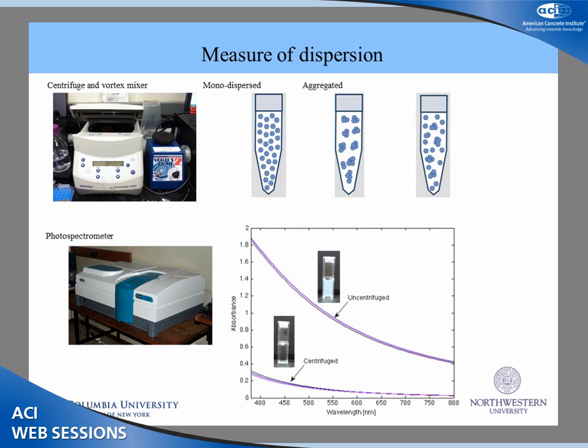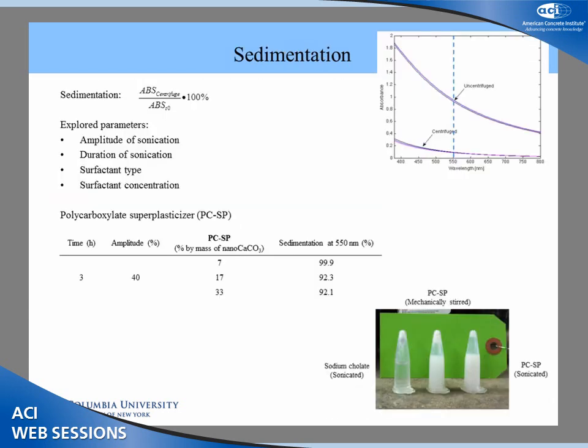So to illustrate this, if you have a perfectly monodispersed suspension, even after centrifugation, if it's properly dispersed, properly stabilized, it should look the same before and after. Now, if it's highly aggregated, after centrifugation, they're all going to crash out. So you can imagine that if you took the absorbance here, it'll be basically zero. And so there will be a big shift down of the absorbance spectra. Now, if it's a mix of kind of dispersed and then slightly aggregated, after centrifugation, some of it will crash out, but then some of it will remain suspended. And so there will still be a shift, but maybe not as dramatic. So we compared sedimentation or absorbance at a certain wavelength and then got sedimentation as a percent.